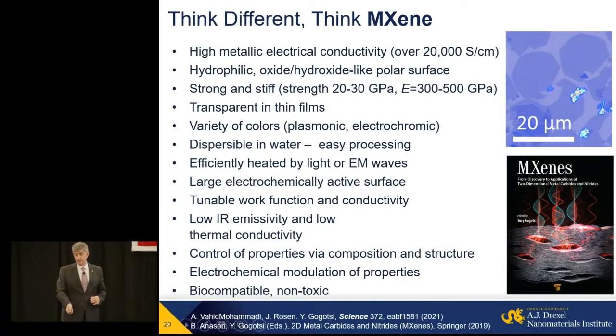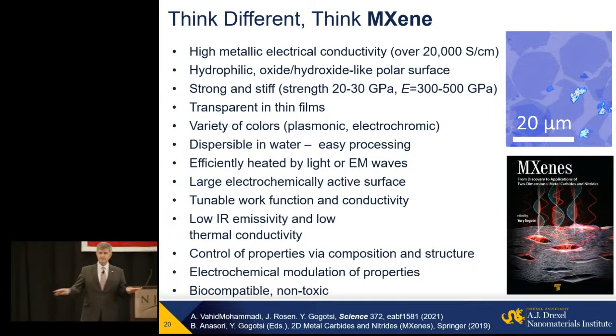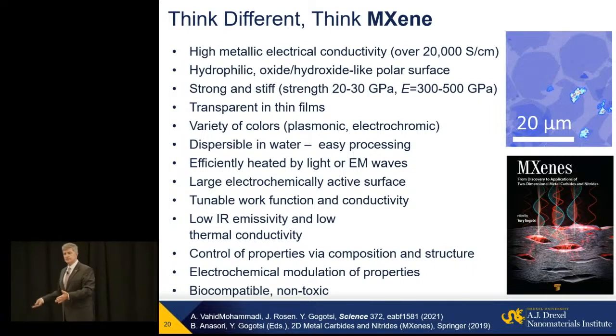But what is important? These flakes are hydrophilic. Again, comparing, they are hydrophilic like graphene oxide. They can be dispersed in water without any surfactant or additive. There is no binder to make a film. You just dry it, and you get a metallically conducting film on the surface, which cannot be done with other materials. Take metallic nanoparticles, you need a surfactant, you need to burn the surfactant, and so on.